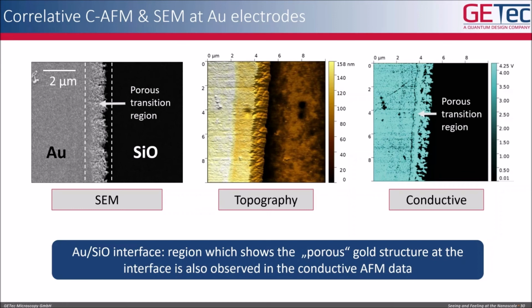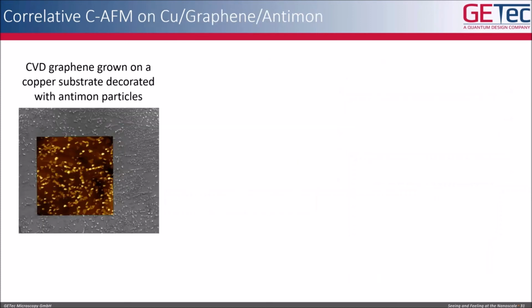This sample is not the most interesting in the world, so I want to show you something much more interesting from the scientific point of view: a correlative conductive image of a copper graphene antimony sample. It's a CVD graphene grown on a copper substrate that is decorated with antimony particles. Here you can see a correlative image—this is the SEM image where you see these antimony triangles, and this is the correlative AFM image.